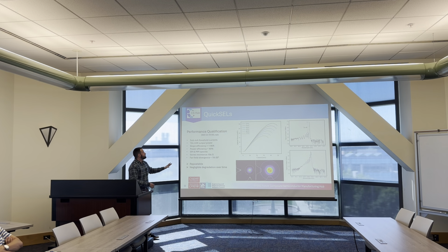So just a quick overview of some of the performance you get out of the QuickSELs. This is all on 940 nanometer epi structures: sub-milliamp threshold currents, tens of milliwatts output power, slope efficiencies above 1 watt per amp, power efficiency of 40%, single mode and multi-mode spectra depending on the oxide aperture, resistance that's representative of a typical standard VCSEL, and far field divergence angles that are also representative. And these results are repeatable, so you can measure the same device many times, get the same answer, and there's negligible degradation over time.